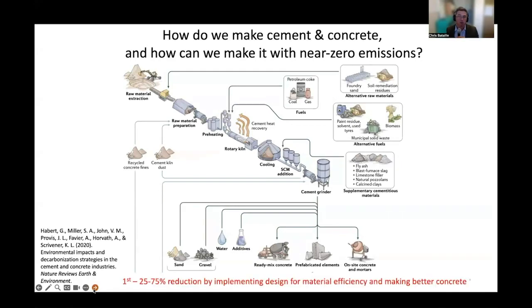First, and this is the one I found one of the most interesting digging into this, is that a 25 to 75% reduction in emissions can be had by implementing design for material efficiency, so minimizing the amount of concrete we use in buildings, and just making better concrete, mixing it better so that we minimize the amount of cement holding together the sand and the stones, the pore space. So you can make a wall that's a foot thick or 30 centimeters thick or 15 centimeters thick, and it can be just as strong if it's better mixed.